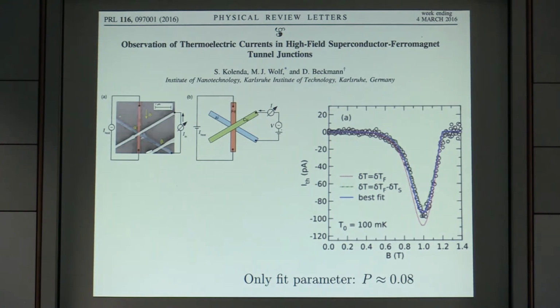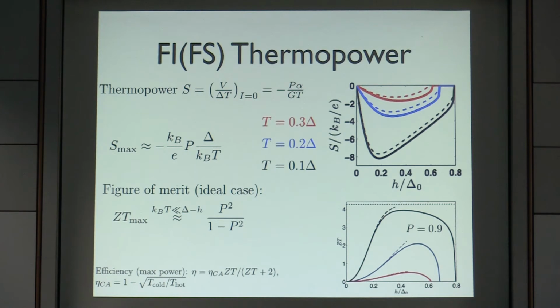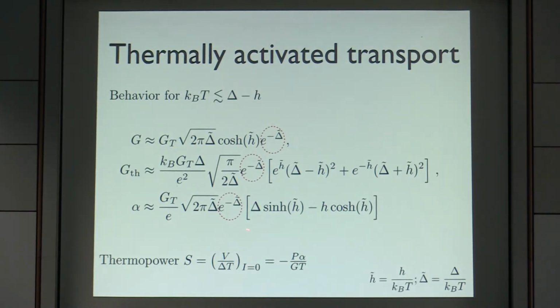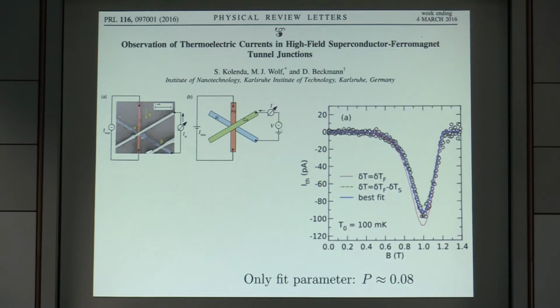Obviously, if the exchange field is 0, this alpha should be 0 also in our case here. So if you put h to 0 in this expression, you get 0. These circles here are what they measured for the current as a function of the applied magnetic field, which translates to exchange field, and the theory prediction is the red curve here. The discrepancy is not resulting from theory; it's rather the fact that they overestimated the temperature difference because some heat also leaked to the superconducting side. So it fits perfectly in there. Actually, I'm saying that the only fit parameter is the polarization. Actually, this is not true. They separately measured the polarization already.